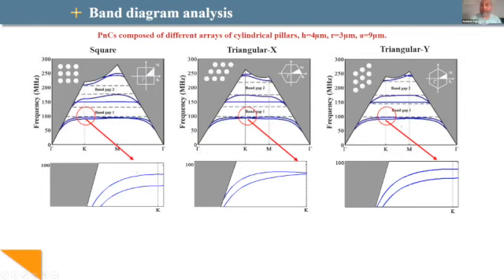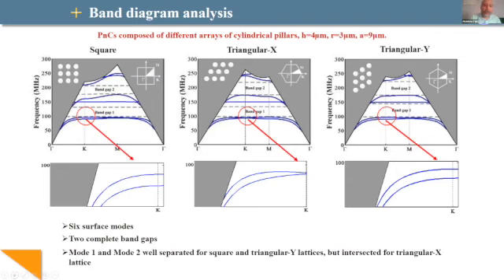And you can see from this scheme of the phononic crystal that we have parallel lines, and this gives us exactly the same result. But when we see the triangular X, the wave doesn't see parallel lines, but lines like a zigzag, and this modifies completely the interaction of the wave with the phononic crystal.